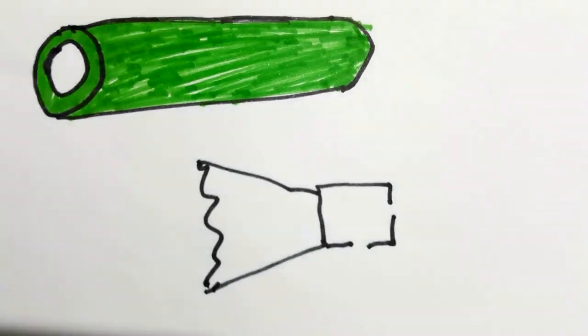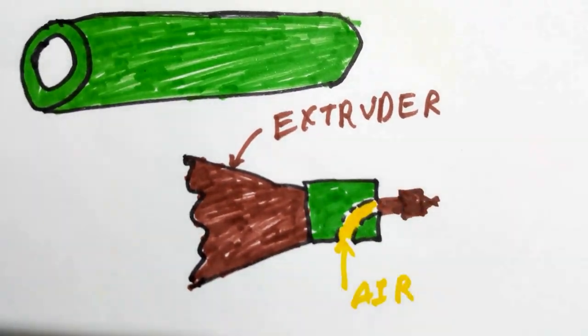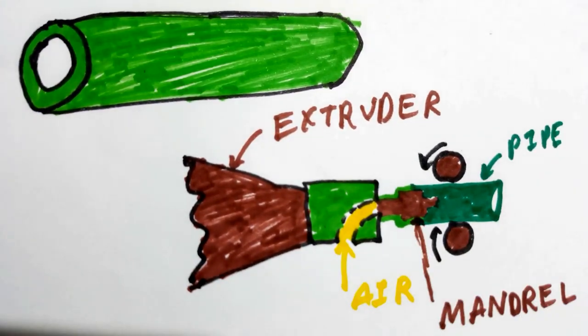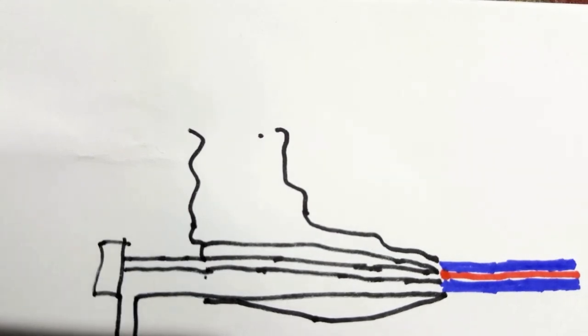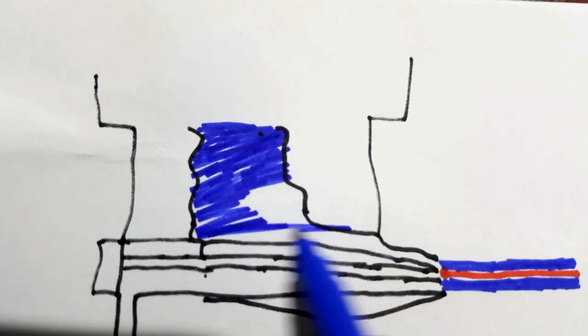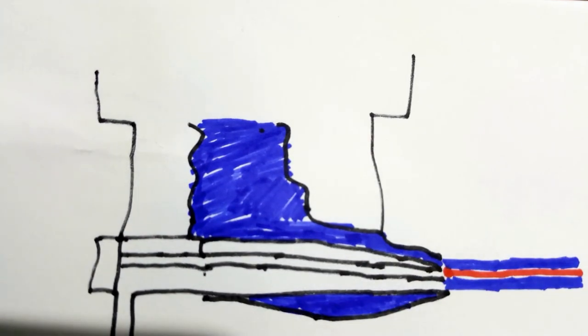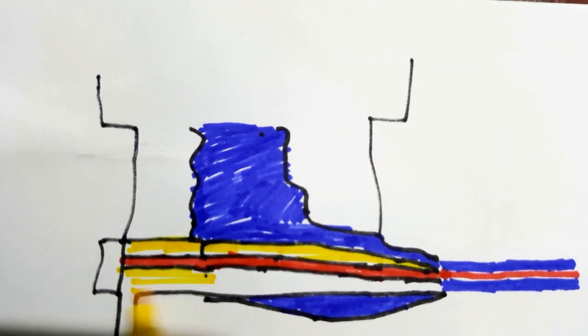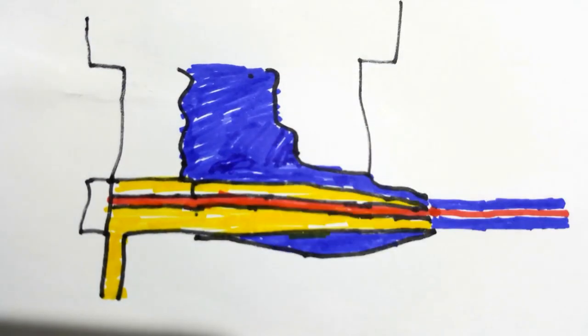Extrusion of pipes is similar to film formation, only here, they are held in position by a mandrel. The coating of wire and cable for insulation purpose is one of the most important polymer extrusion process. Here, the polymer melt is applied to the bare wire as it is pulled through a die at high speed. For adhesion of coating, a slight vacuum is drawn before the polymer and wire.